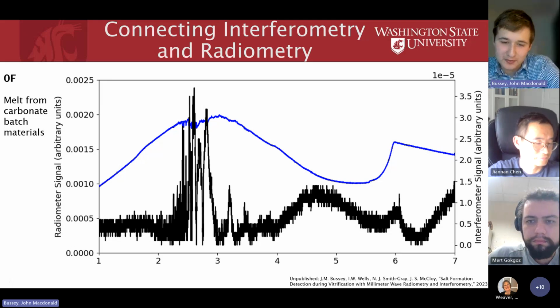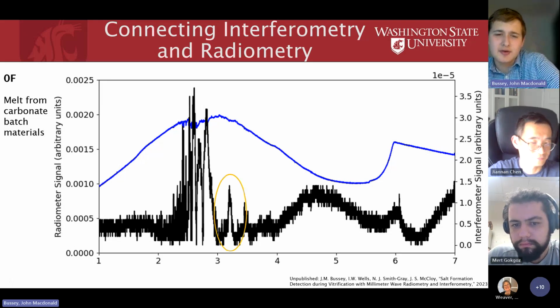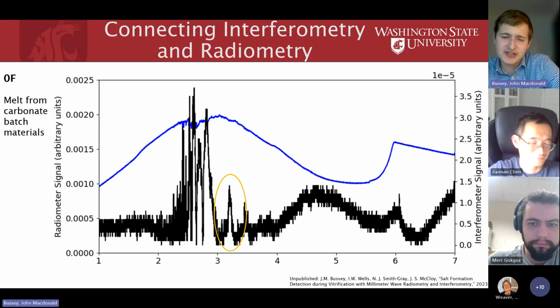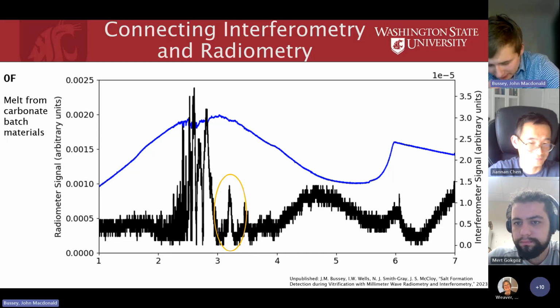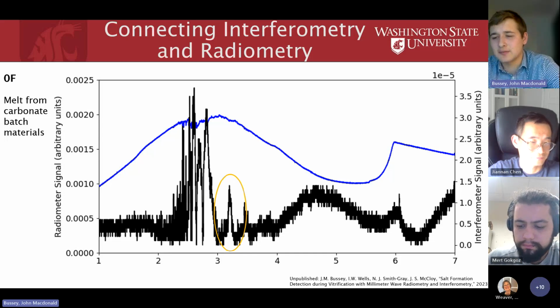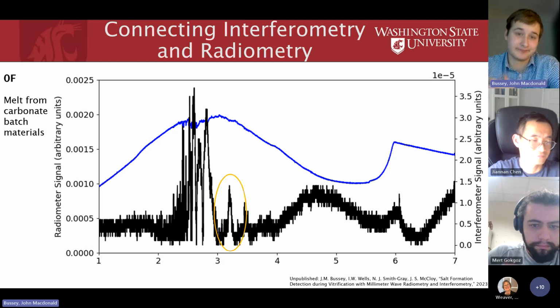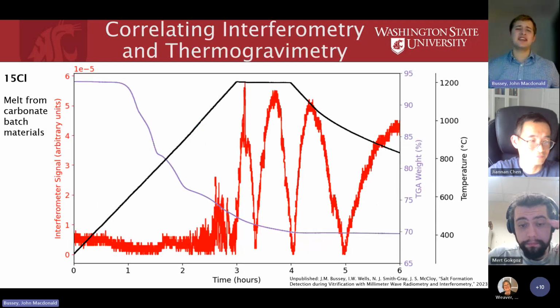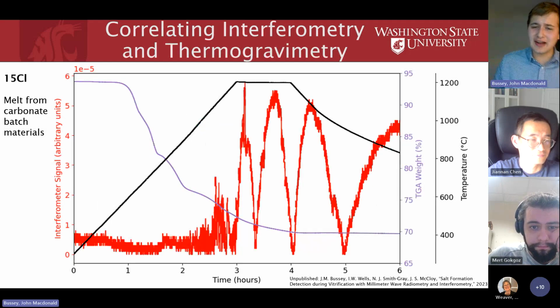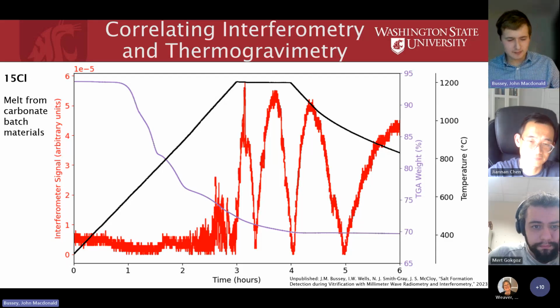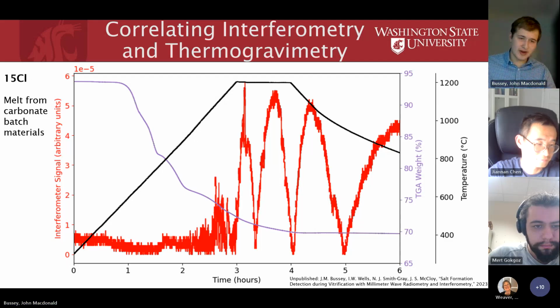So when we think salt's forming, we see another peak here that we think we can assign to salt formation, because we see it in all the glasses that form salt, and we don't in the glasses that don't. So the other thing we did is we did some thermogravimetric analysis on the same batch materials at the same temperature profile to be able to connect the weight losses with the surface height change.